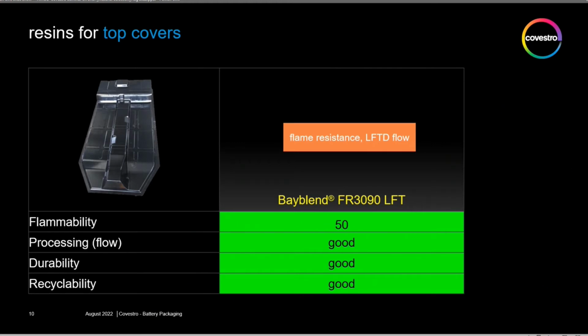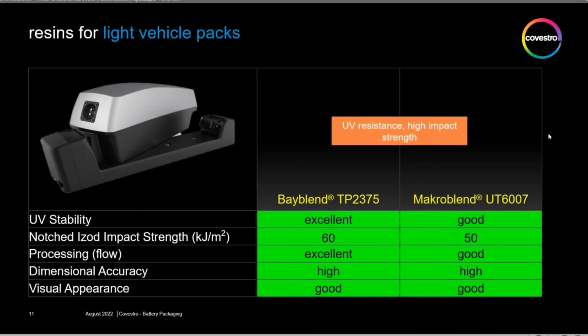All right, next up is the top covers. This is something we don't see as often, but it is a way to really give good protection to battery packages. And this is often in an application that is too large to injection mold. So for that, we need a specialty grade, and we need to use a special type of processing called long fiber thermoplastic, where basically the glass fibers are impregnated with the polycarbonate material. And you can make a big sheet that you can practically thermoform into this shape. And so our grade for that is very specialty. It's Bayblend FR3090 LFT for long fiber thermoplastic.